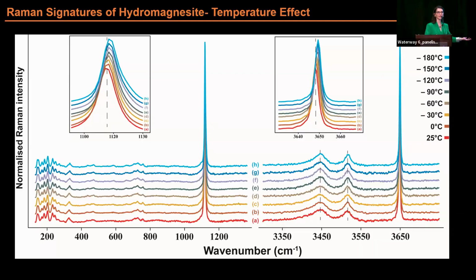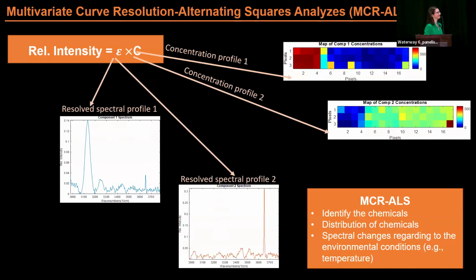And here is the temperature effect, on the hydromagnesite gravels powder that has been exposed to the temperature. What we have seen in these results is that the temperature has nearly no impact. We have only seen a very slight shift, from 1 to 3 per centimeter. During the temperature change, we haven't seen anything else, except that the structural water crystalline bands become much more distinct, depending on the OH coordination region. We haven't seen anything else observable here.